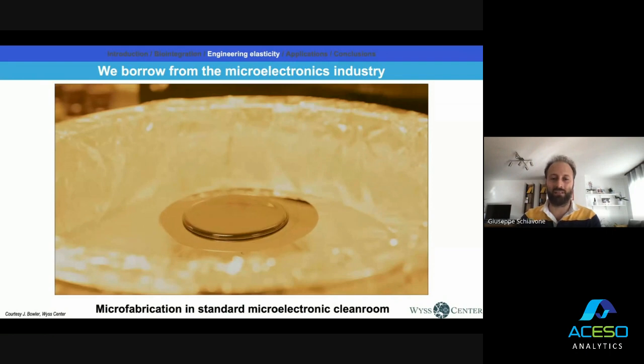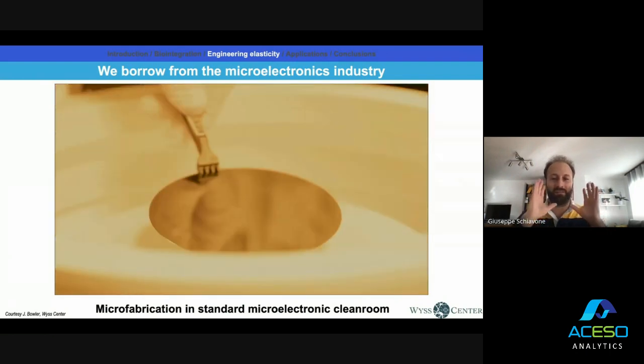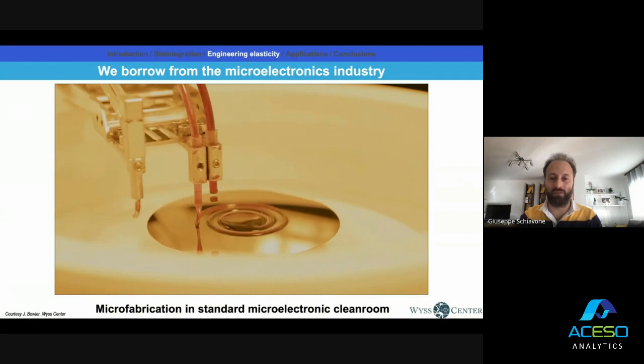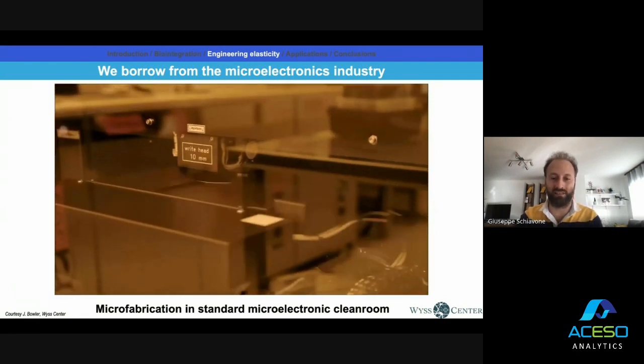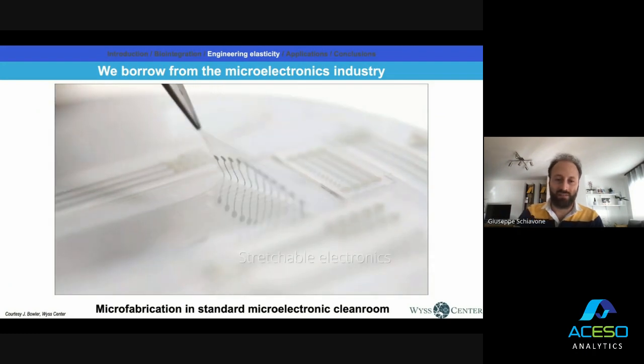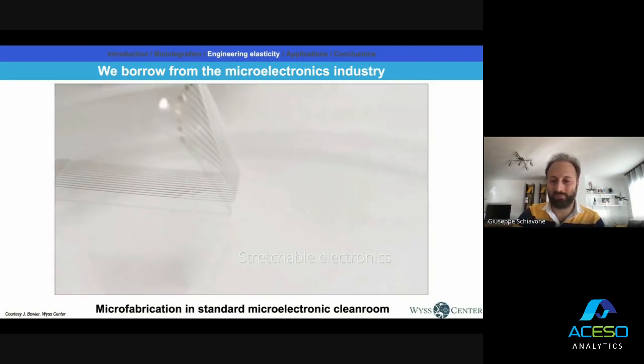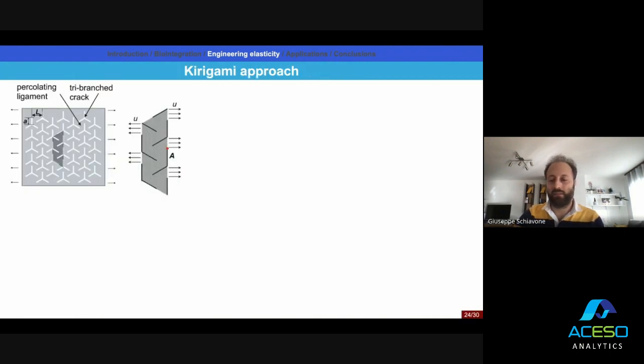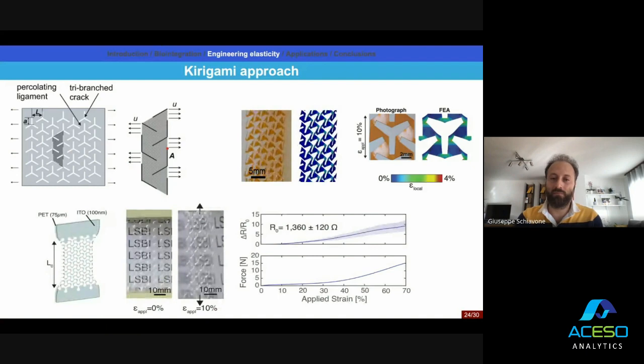So we have several semiconductor processing capabilities there, but we're really tuned for use on polymer materials and soft materials. So this is one of the devices being manufactured. So when we take control of the microstructuring properties, we're not just letting the materials deposit with a random cracked pattern, but we're actually introducing a really precise structure at the microscale that enables us to also fine-tune the mechanical properties and electrical properties of these films.